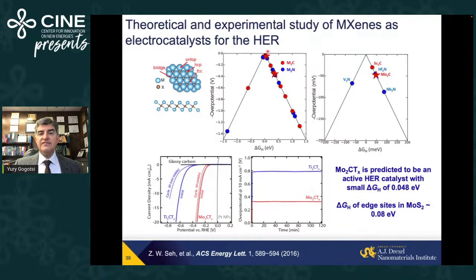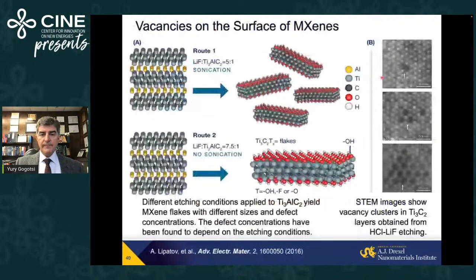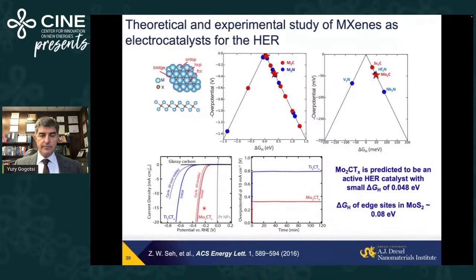What does it mean? They will be good materials for hydrogen evolution reaction, water splitting. And this is again all about designing the right composition. You see, overpotential for water splitting can range from minus 1.4 to very close to platinum, close to zero. Mo2C, for example, has been predicted to be a good one. And indeed, it shows much better performance than Ti3C2. But it's still not at the level of, say, platinum.